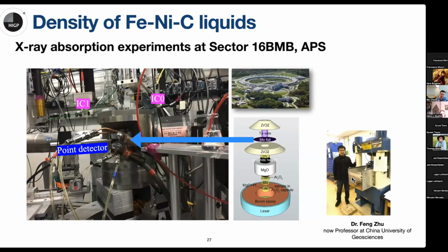We utilized the same experimental setup, but we used another technique called X-ray absorption to measure the density of iron nickel carbon liquid at high PT conditions. This is again led by my former postdoc, Dr. Feng Zhu. In the experimental setup, the sample is in an alumina capsule. We also have this alumina as a reference for the density, and the MgO plus platinum is a pressure marker.